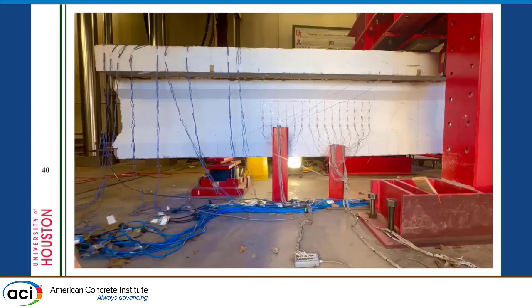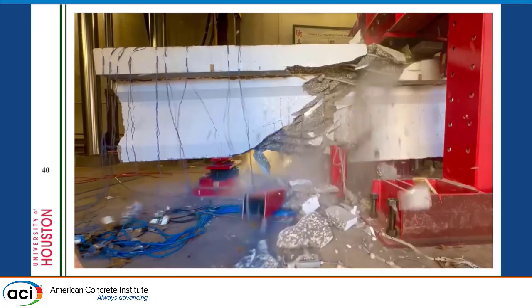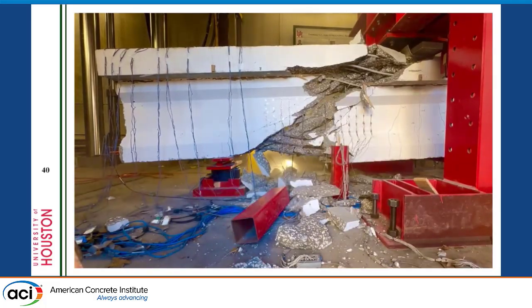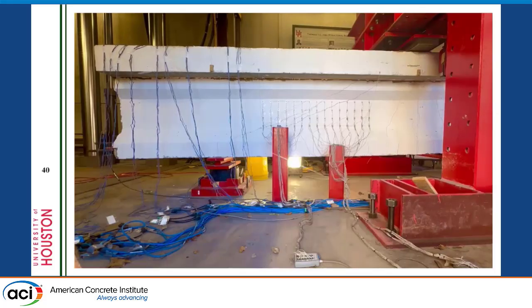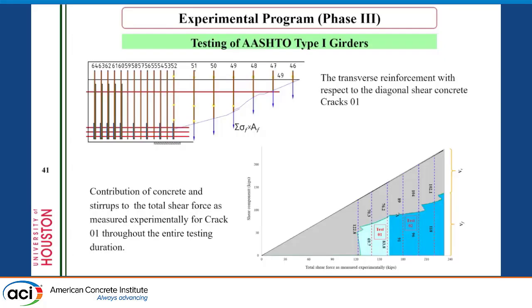And this is the shear test. Basically, this is not for the stainless steel stirrups. This is for the GFRP, because we had GFRP, stainless steel, and regular stirrups. I brought this here to share what we got in terms of the Vc and the Vs. Usually when we say the crack appears, there is no contribution of the concrete anymore, and just the steel carries everything. But here we tried to examine it experimentally: does the Vc still contribute? And you can see here the Vc is still contributing.